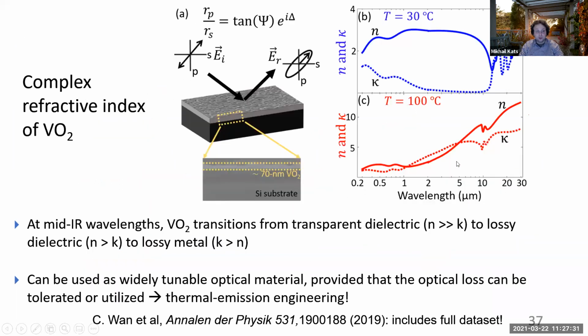In the case of VO2, the complex refractive index in the infrared, which is where we care about, changes really dramatically going from room temperature to high temperature. So this is from 30 degrees Celsius, for example, to 100 degrees Celsius. These are spectroscopic ellipsometry measurements that we did at UW-Madison from about 200 nanometers up to about 30 microns. This is incredibly broad. And actually, if you're interested in using this data for your own design and simulations, you're welcome to check out this paper we published in 2019, which if you go to the supplementary information, you have the full data set.